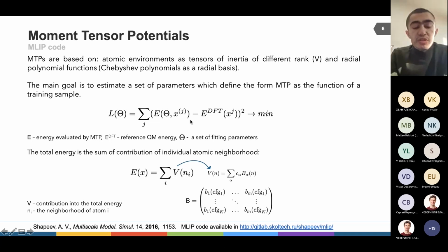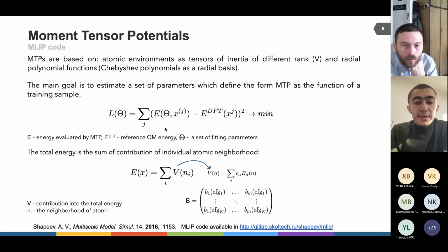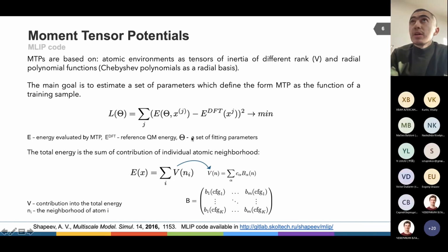This type of potential accounts for local atomic arrangement and expands the total configuration energy into the sum of contributions of individual atomic environments. We can also call this atomic neighborhood. Each neighborhood contribution is expanded through a set of basis functions. When fitting to the energy values, we need to solve the overdetermined system of linear equations, and each equation of this system is produced by a certain configuration, and it can be called the active learning set.